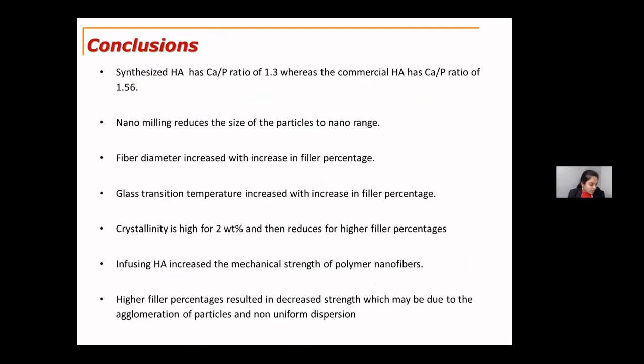So coming to the conclusions, or summarizing this, the synthesized hydroxyapatite has a calcium to phosphorus ratio of 1.332 compared to the commercial one, which has 1.56. And the nanomilling, which is employed to reduce the particle size, has definitely reduced the particle size to nanoscale. And the fiber diameter also increased with the increase in the filler percentages. For the higher weight percentages, we see that agglomeration happened inside the fibers, and the fiber diameters were extremely high compared to the 1 weight percent and 2 weight percent.